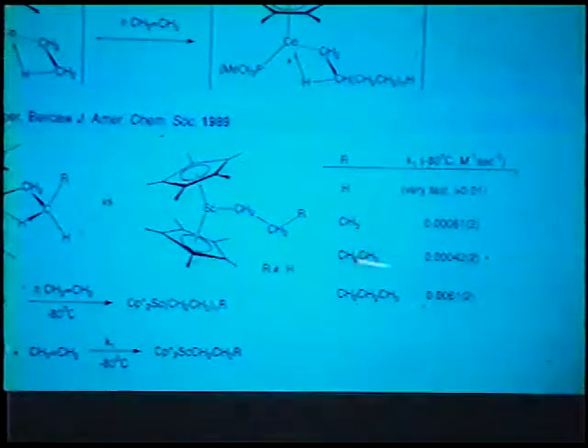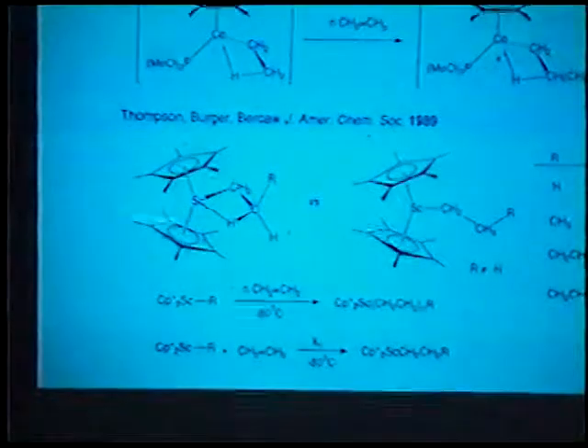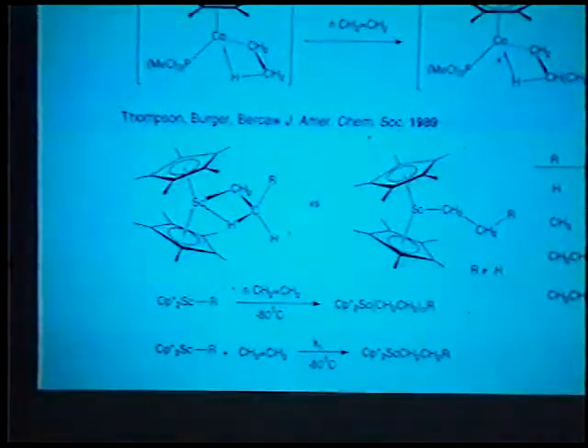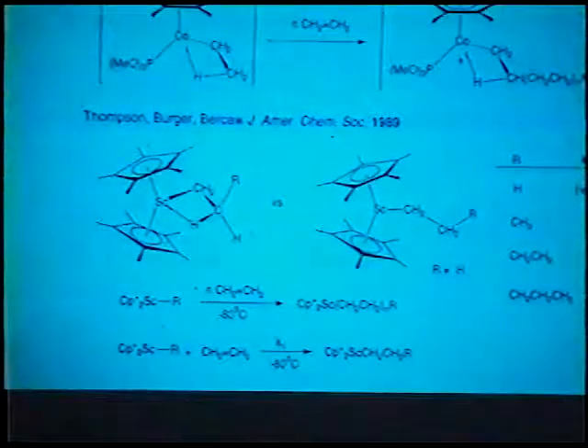Interestingly, the ethyl complex has a beta-agostic interaction in its stable form, and the propyl has a normal structure, almost certainly because there would be necessarily a bad steric interaction between the methyl group and one of these methyl Cp's in the propyl group. So the features that encourage olefin insertion are really the electron-deficient nature of the metal, and the beta-agostic interaction is simply reflecting that. But in fact, the implication here in the scandium system is that the beta-agostic interaction actually interferes with the olefin insertion step, and presumably that CH bond must be dissociated before ethylene is inserted.